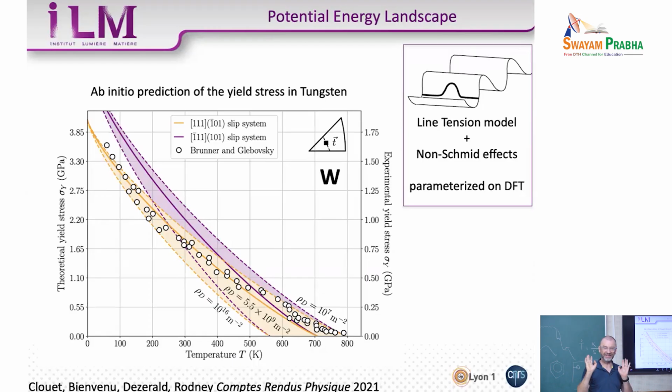Now that's something that you should keep in mind. If you try to do materials design for BCC metals from the atomic scale and sell it to industry, your stresses will be 3 times too big. So that might be hard to sell, but we don't know why. We don't know why our simulations are off. So this scale here is okay for comparing these simulations and experiments. This scale is wrong by a factor of 3.